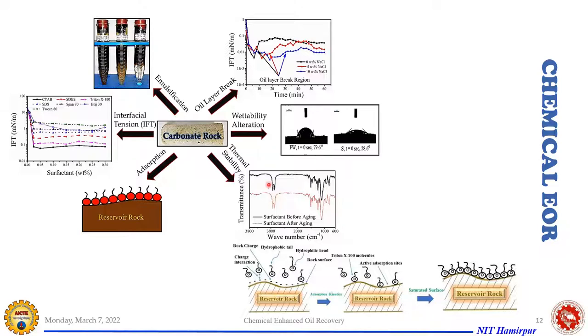To further verify that, we have identified the IFT value of this surfactant before aging and also after aging, and we have received more or less the same IFT value, which clearly indicates that the surfactant is stable up to a certain temperature range. And then, as I told you, adsorption is an inevitable process, it will occur, and we need to look into this criterion so that we can have minimum adsorption in our reservoir. So we have also investigated the adsorption studies. This is one more paper available in my profile, where you can see how adsorption is affected by temperature, salinity and the reservoir properties.